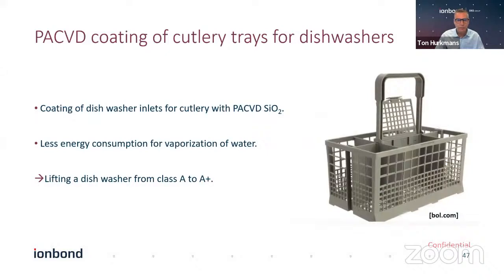Another nice example that we found is not being done at our company, but you see also PACVD silicon oxide coatings on the trays that go into dishwashers. And apparently it gives us less energy consumption when you're drying your load. So it makes it easier to vaporize the water of the load. Small things can help and go a long way if you do it every day. And this gives a lift in the energy classification system for this.